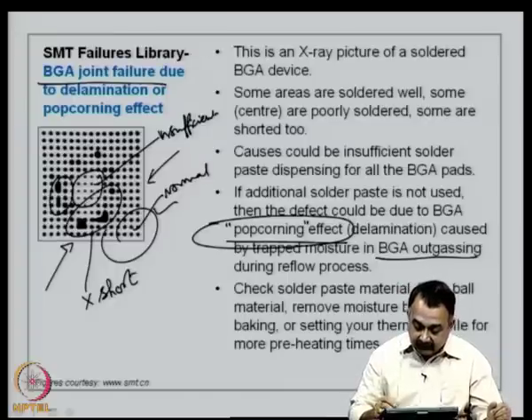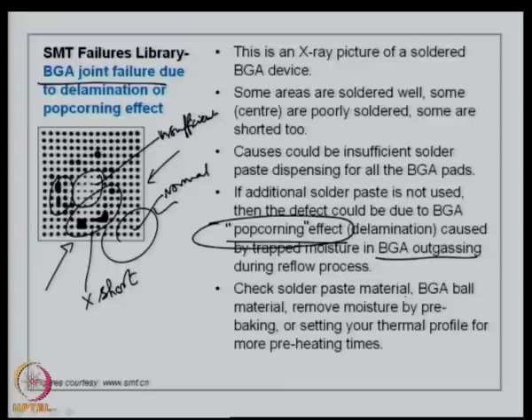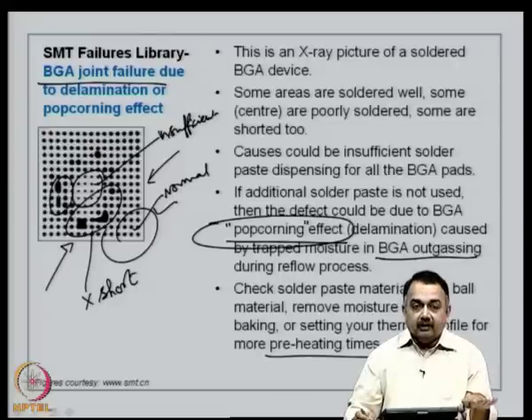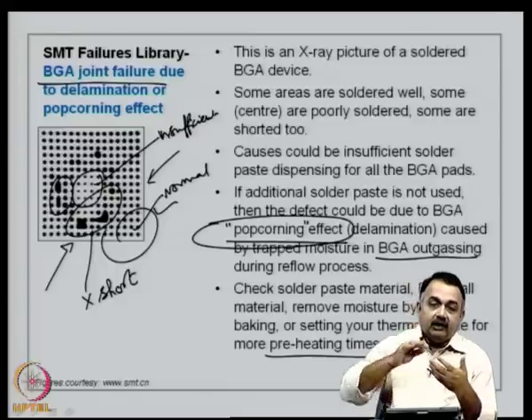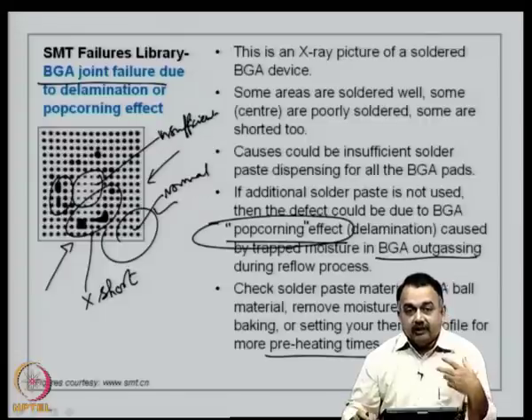So, check the solder paste material, BGA ball material, remove moisture by pre-baking or setting a thermal profile for more preheating times. So, if you have not done pre-baking, to be on the safe side, in your thermal profile, spend more time for the board to be in a pre-bake area, and then go into a soaking zone where the solder paste gets activated, and then go to the reflow zone where you attain peak soldering temperatures.